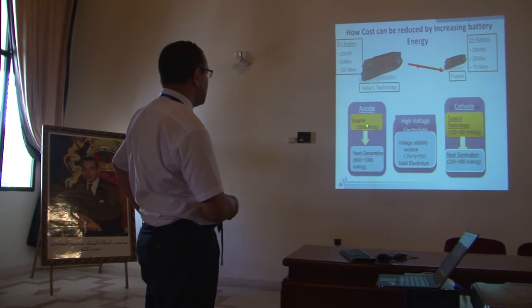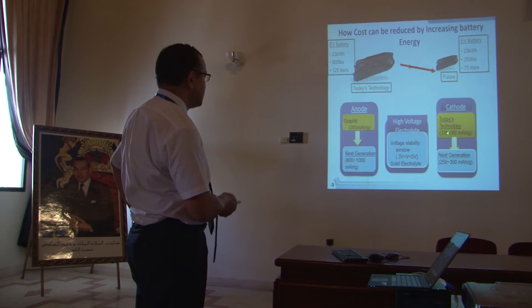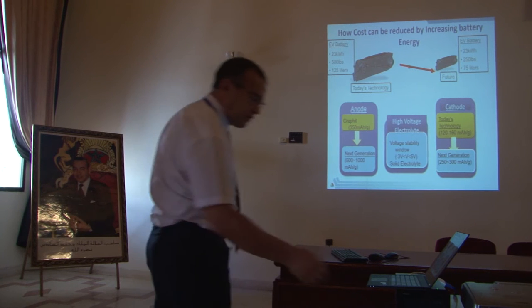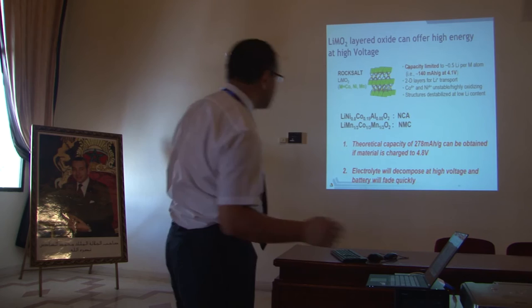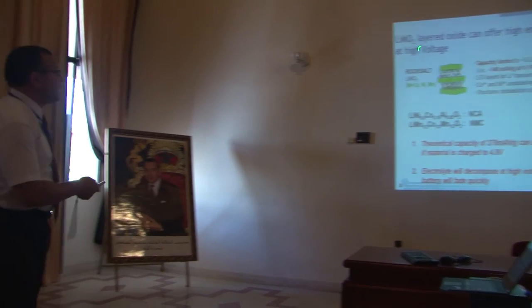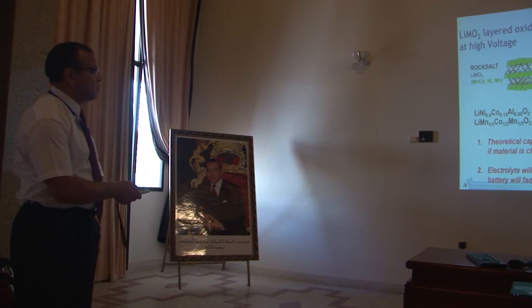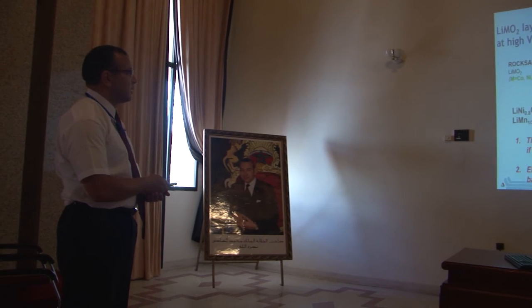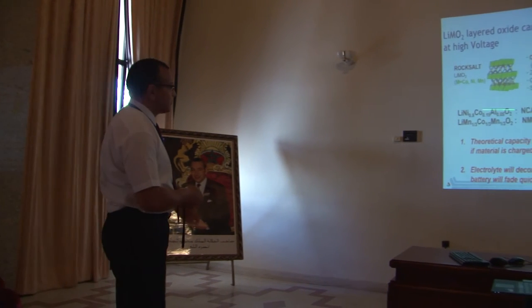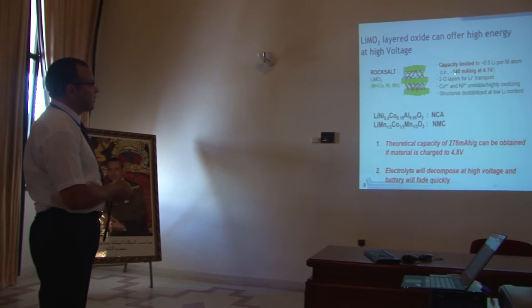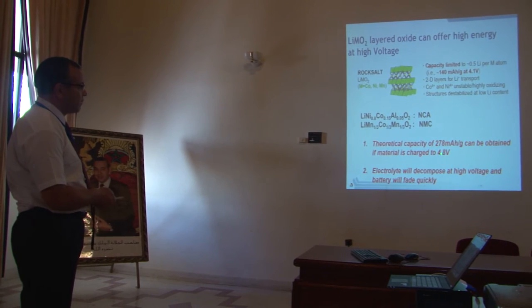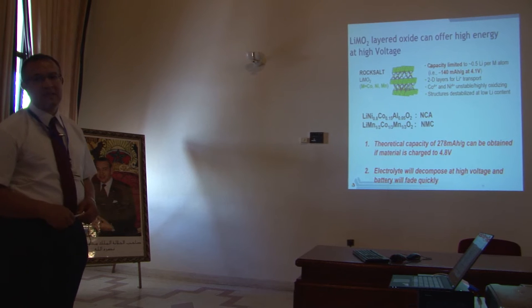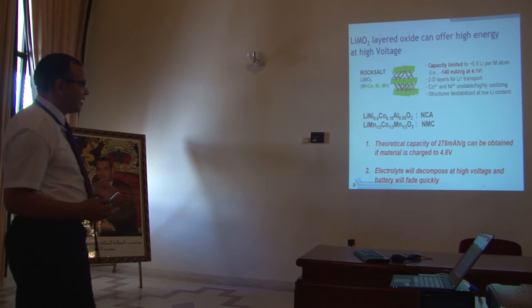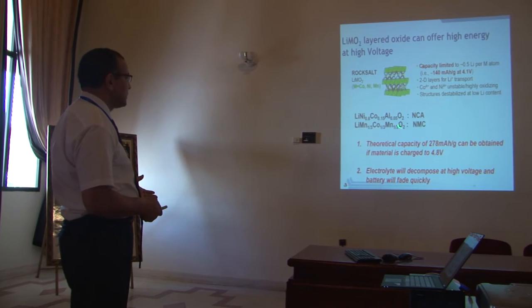So what I'd like to do today is show you an example on the anode, an example on the cathode, and an example on the electrolyte within these 20 minutes, whatever is left. So if you think, for example, of the layered oxide, the NCA, which is used now in hybrid electric vehicles for power application, or the NMC, and you charge at 4.1 volts, that's the operating voltage of this material, because of their instability you get about 140 milliampere hours per gram. But if you go higher in voltage, you can achieve much higher capacity, which we are targeting. The problem is at high voltage, these materials decompose.